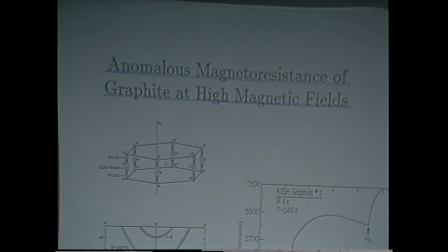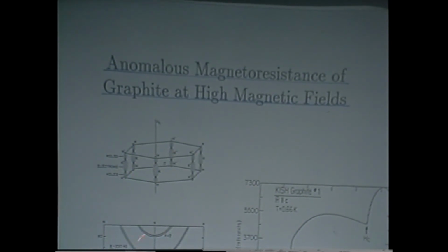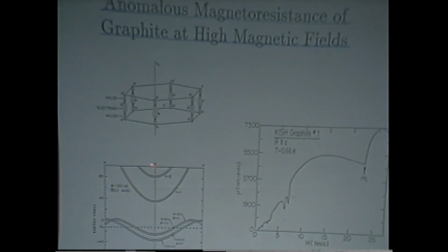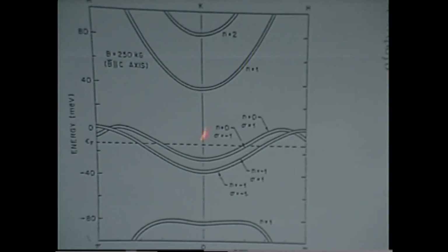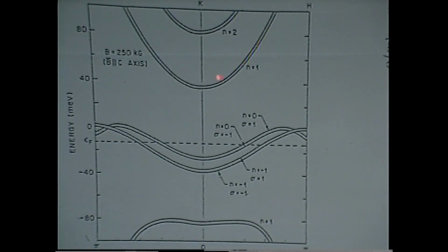And it was on anomalous high field magnetoresistance. When you think about the problem from a one-electron point of view, you have all these Landau levels going through the Fermi level, and the n equals 1 level, that's the standard one. That's supposed to be the last Landau level to go through the Fermi level. That goes through at about 7 Tesla. And spin splitting is a doublet, so you see 2 little pips.